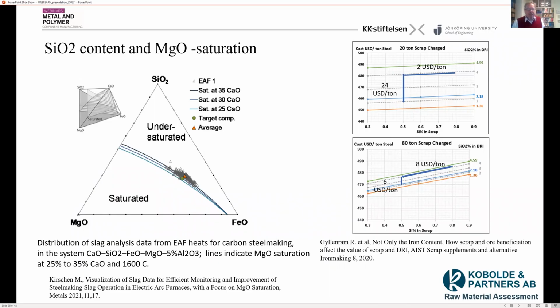And when you look at the electric arc furnace, and you look at the slag formation in the electric arc furnace, you can see from this slide that the silicon content in the DRI is really important for the economy. If you look at the picture to the left, if you don't match the silicon that goes in together with the direct reduced iron with lime and magnesite, MgO, then you will get an undersaturated slag. That means that you will consume MgO from the lining, and that's extremely costly.